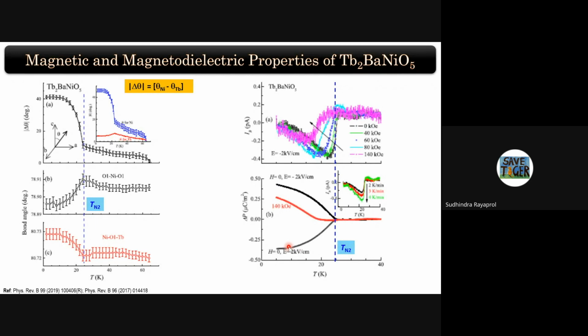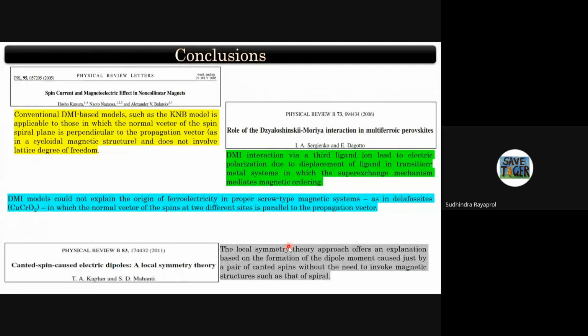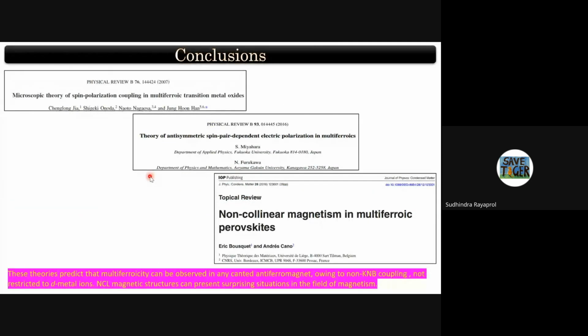The magnetodielectric effect is about 18%. So if you try to understand this on the basis of conventional DMI models, which is present for non-collinear magnets, it fails to show that, because the structure is non-collinear, but it is not a spiral one as predicted by DM interactions. If you look at non-collinear magnetism in perovskite magnets, what the theory needs is for the role of rare earth ions like the terbium 4f ion to be investigated, and right now that is actually lacking in the theory.